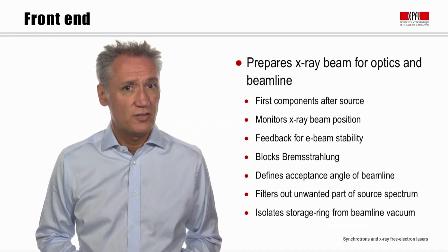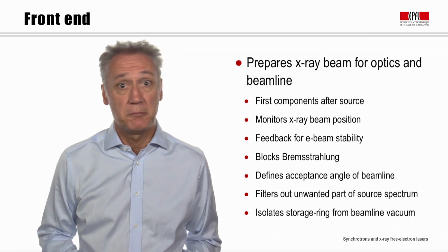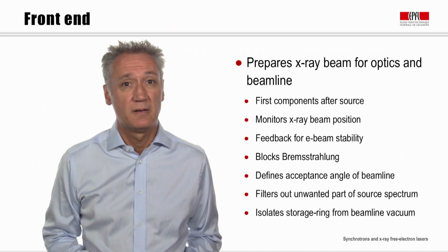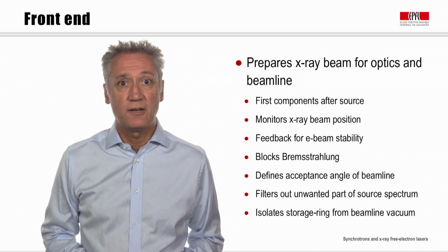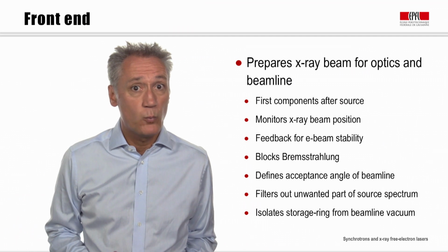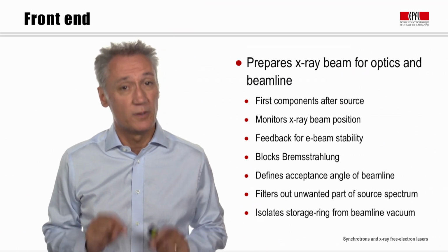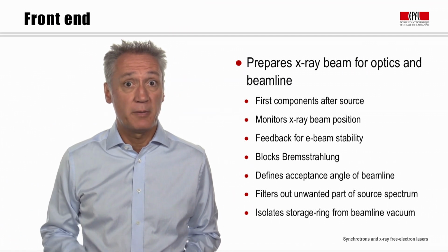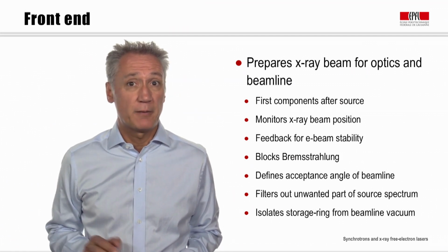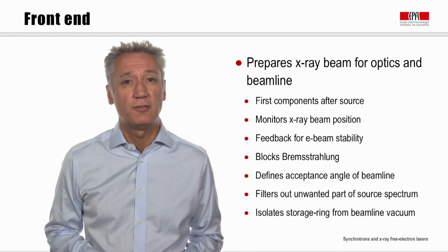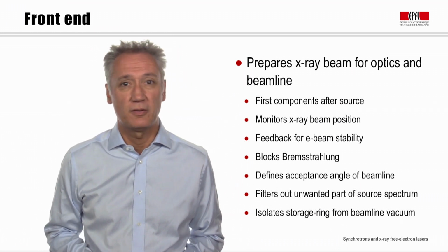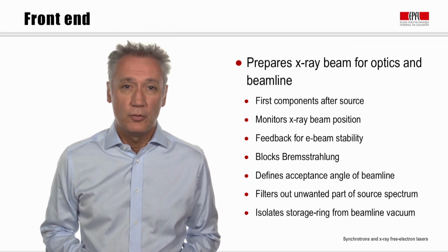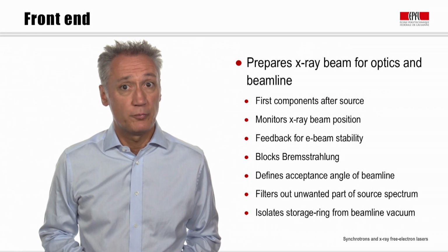Due to the very high energies, Bremsstrahlung is not deflected by, for example, the first reflecting mirror, but will simply pass straight through it. So the desired synchrotron radiation, with photon energies typically well over 3 orders of magnitude lower, is deflected by the mirror, so the Bremsstrahlung blocker can be placed behind this mirror. The Bremsstrahlung blocker needs to be made of a block of heavy metal, typically tungsten, with a thickness measured in several tens of centimeters. Only such a dense obstacle is sufficient to absorb Bremsstrahlung.